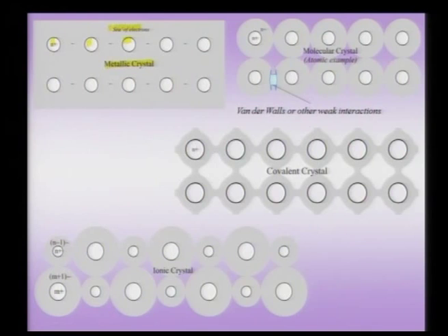On the other extreme is the ionic crystal, wherein all the charge is localized around the ions and there is not much charge in the interstitial region. The covalent crystal is a special case of this kind of presence of interstitial electron density, and this is, as you can see, localized along the direction of the bond. So this interstitial high electron density is what we call the covalent bond.